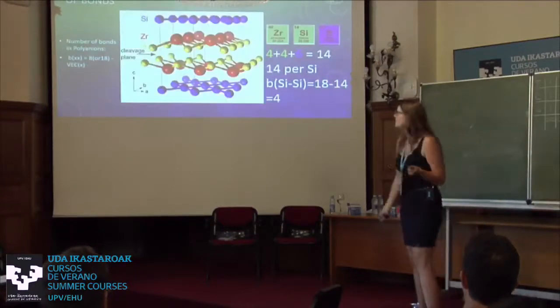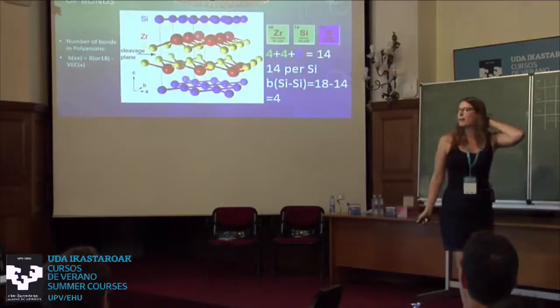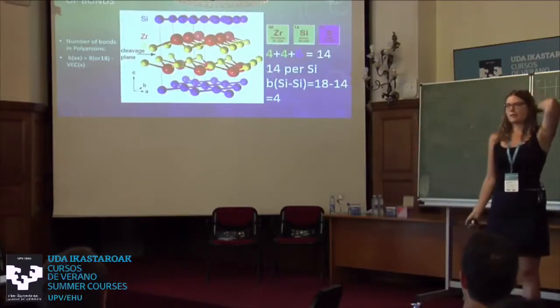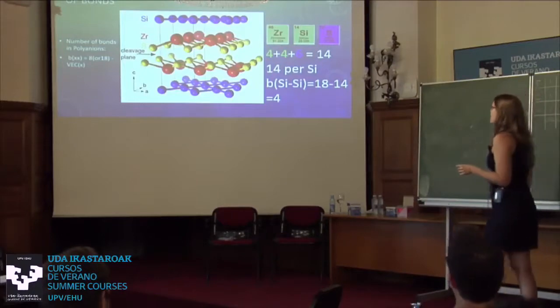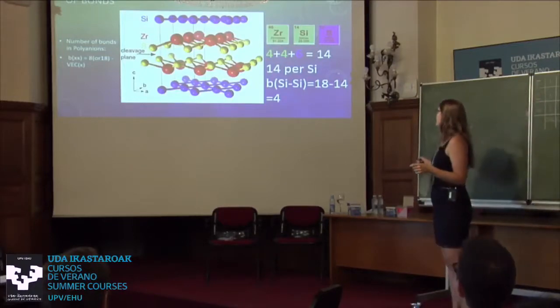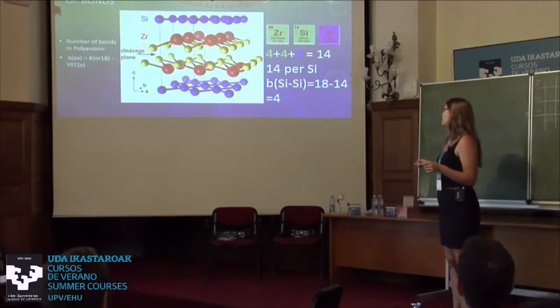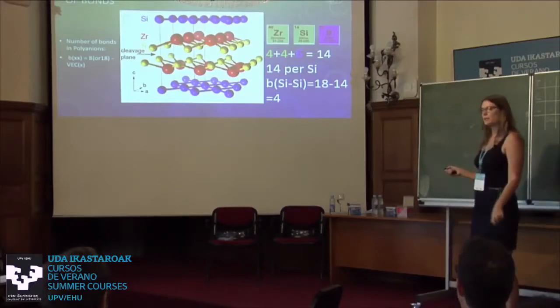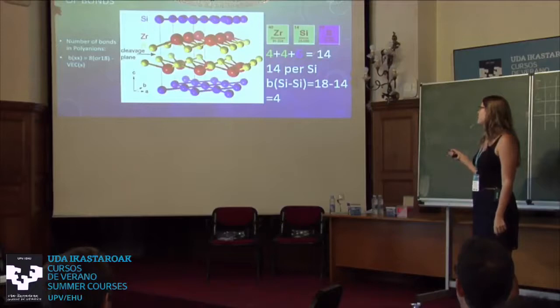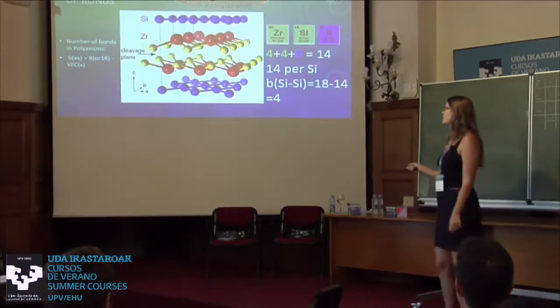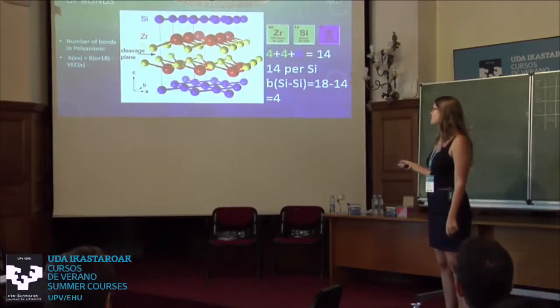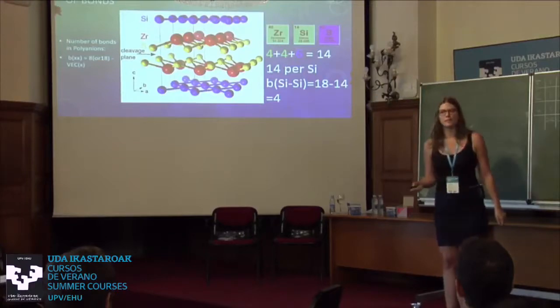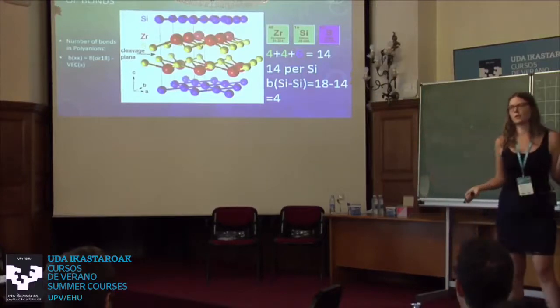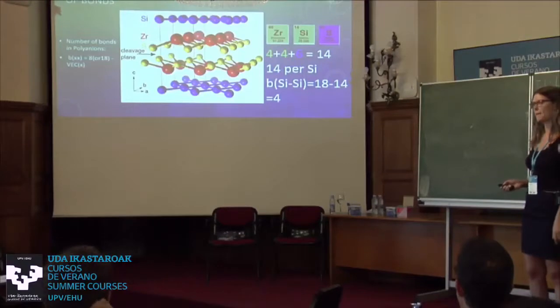So why am I telling you this? Here's a Dirac line node material you might have heard about. This is zirconium silicon sulfide, and if you look at this material, you will see that it's only charge balanced if you consider the Zintl concept rule. So if you count the electrons, you count 14 per silicon. And so if you subtract this 14 from 18, you get a bonding order of 4. And you can see that here, those are the silicons. Each silicon is bonded to 4 other silicons. So therefore, this is a charge balanced compound, although it would appear metallic. Okay.